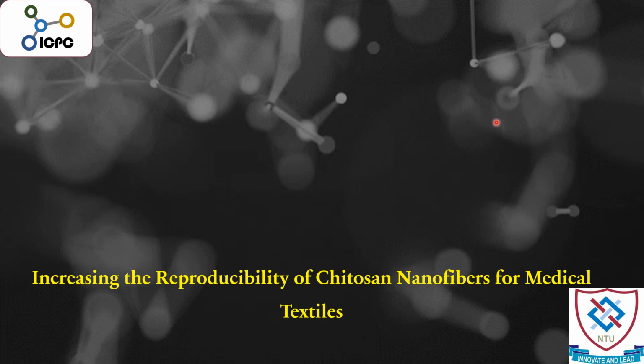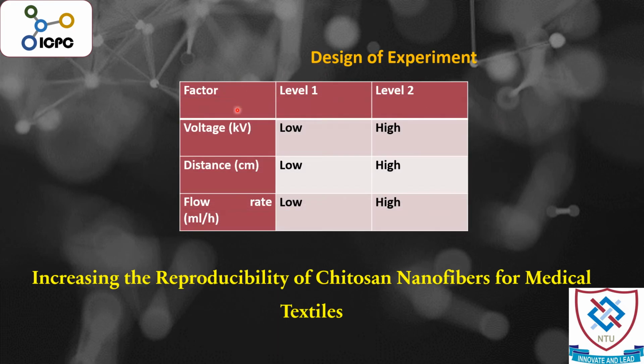So for this we selected Taguchi based design for optimization. We selected voltage, distance, flow rate at low and high levels according to the literature, so that we can optimize the results and reduce the standard deviation as much as possible.